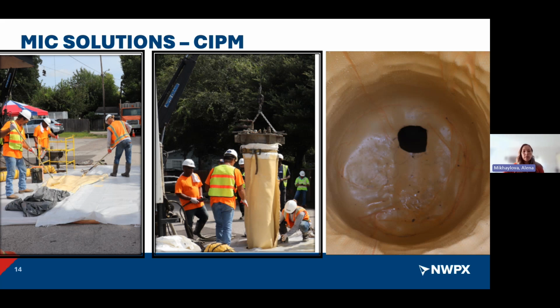And once they lower it all the way to the bottom, they introduce the air so it expands and adheres to the walls, and then they cure it with steam or UV lights. The UV light option is typically less smelly, so it doesn't create much disturbance for the neighboring residents. Whereas the steam curing is more smelly, and there are styrene VOC gases. So this solution is very good for I&I. It kind of seals infiltration with this method. From the sources they have found, it costs about $500 to $700 per linear foot, as compared to $100 to $150 for cementitious materials.